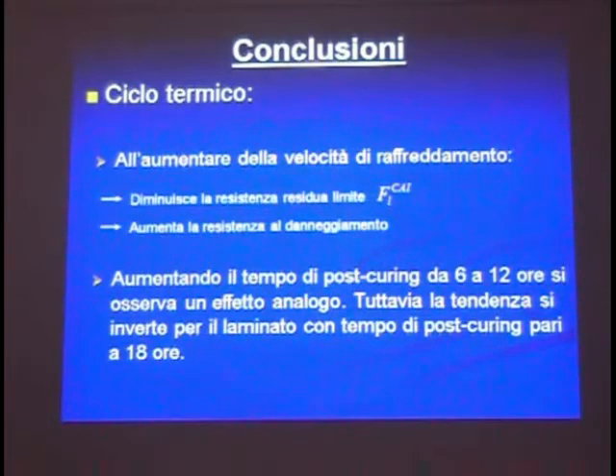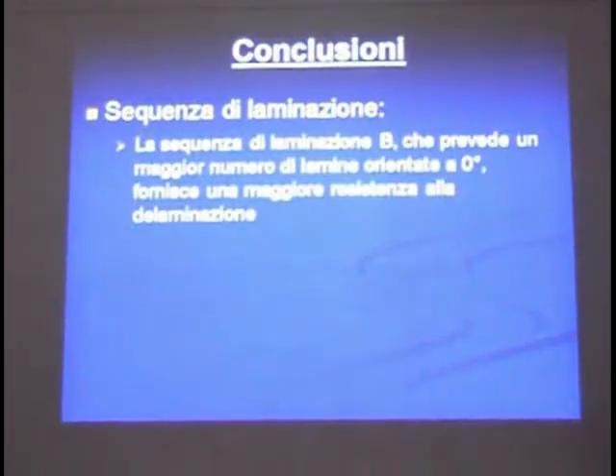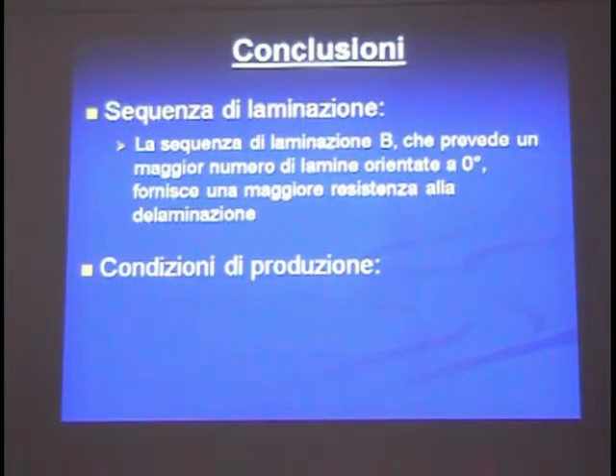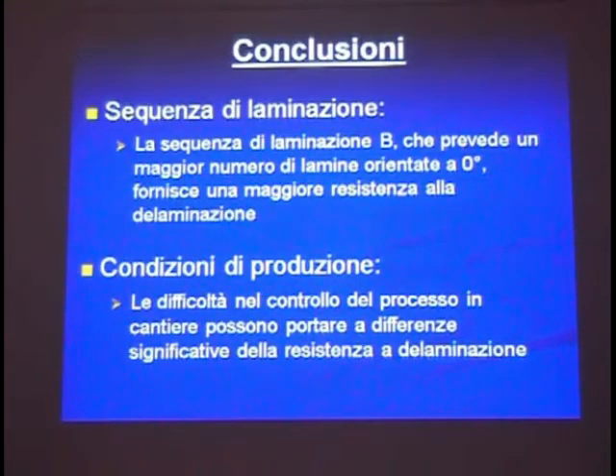So to summarize, if you increase the cooling rate during processing, you get a lower limiting stress, but you're more resistant to further damage increases in the samples. And if you increase the post-curing time, you get the same effect, although the picture is much less clear. And for the lamination sequence, the higher is the number of layers oriented at 0 degrees, the higher is the fracture resistance. But difficulties in the control of the processing in the shipyard can give significant differences in the